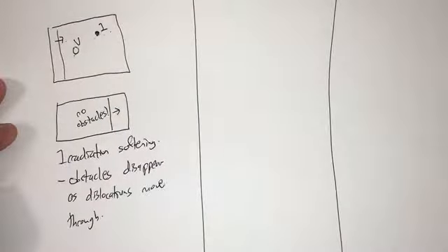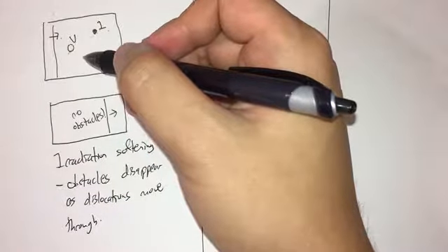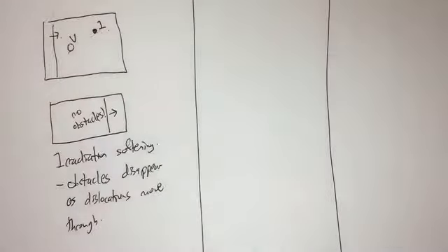So for relatively pure iron, not exactly stainless steel, you can see that radiation tends to harden materials because the first time the dislocation travels through it, there will be obstacles and there will be extra force needed to push it through and cause all these to absorb into the dislocation. But after that, we don't have any obstacles there. So this is irradiation softening.